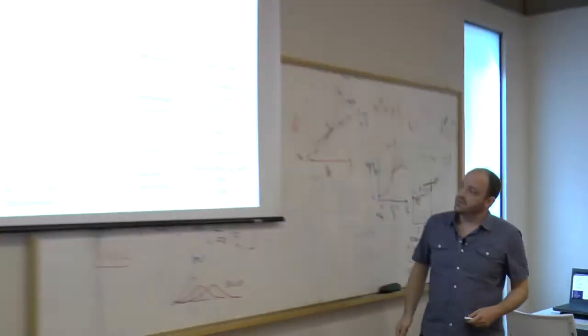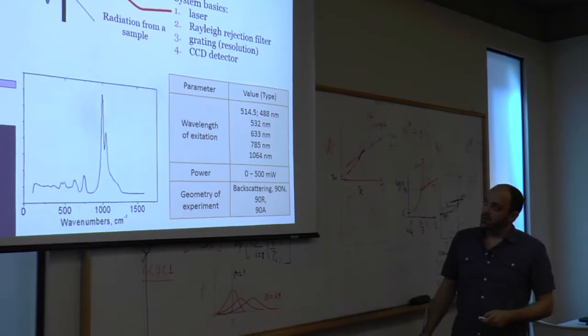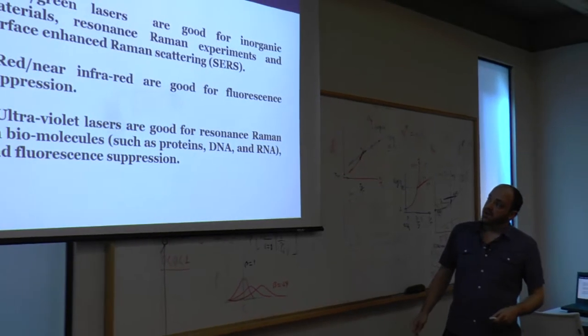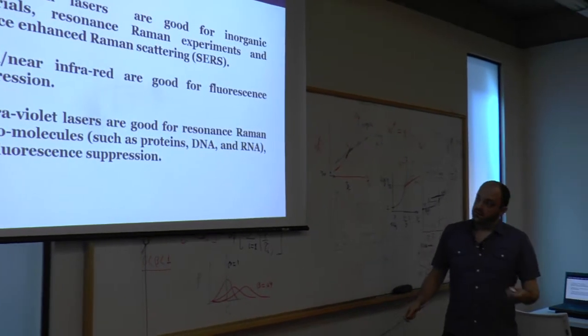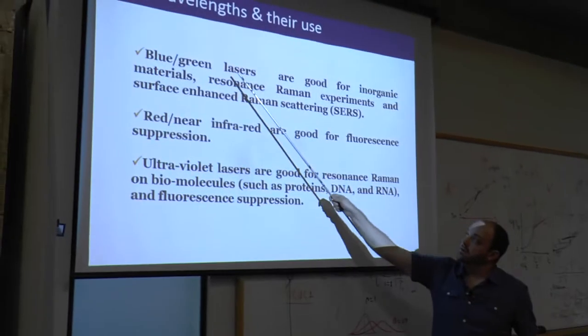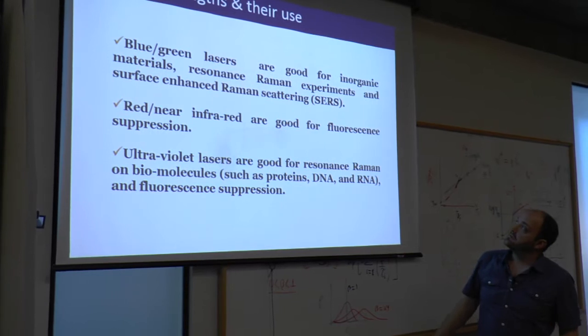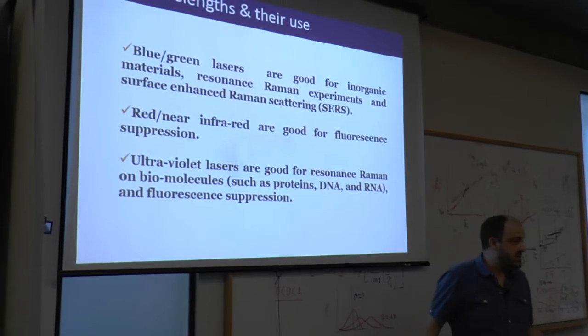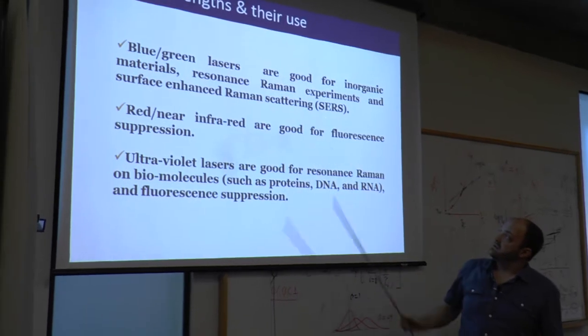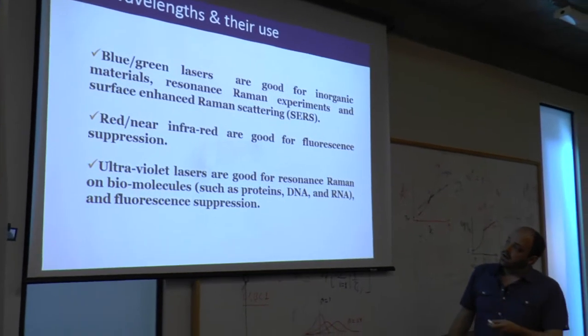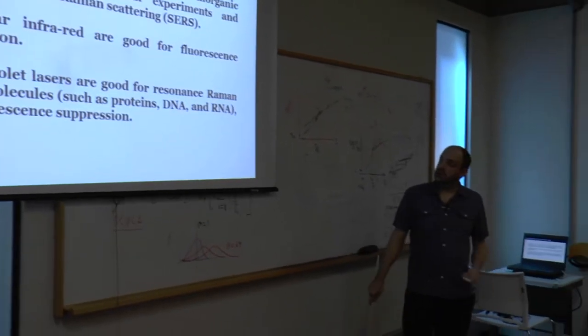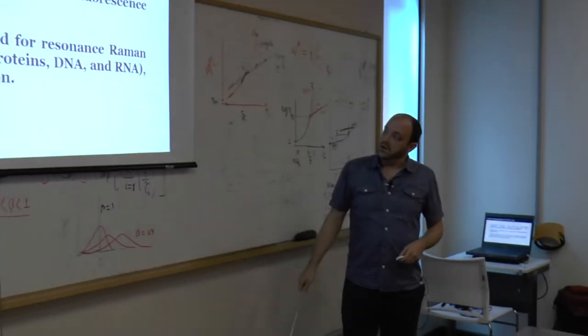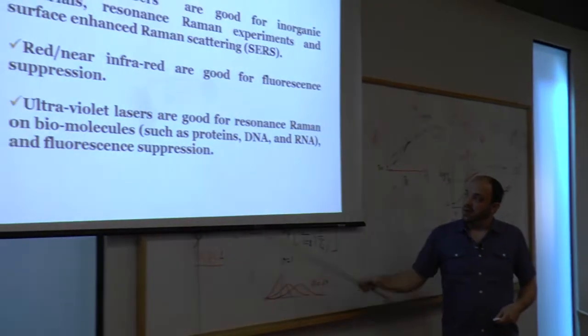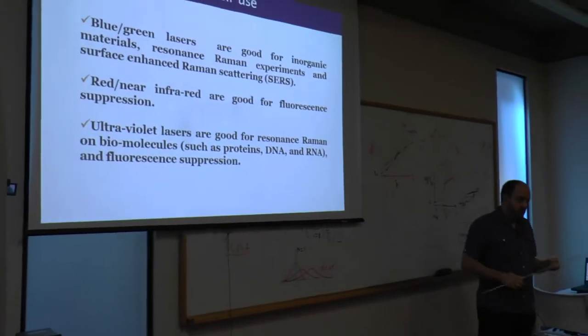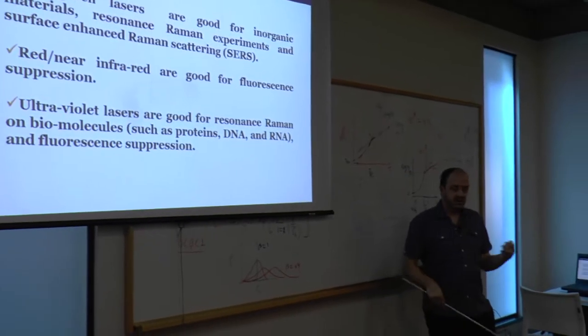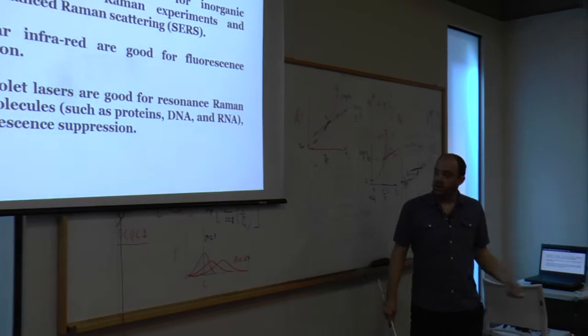There's a bunch of different wavelengths we use and a variety of geometries. The main different uses of the different wavelengths are for blue and green lasers in the higher frequency part of the spectrum. They're good for inorganic materials. These are the ones we typically use for silicate glasses, but it's also used for a couple other techniques. In the red or infrared, it's good for fluorescence suppression. And at the ultraviolet, we can use it for biomolecules, proteins, and looking at DNA. So pretty much any material you want to look at is possible in any state, whether it's biological, inorganic, whatever you like.